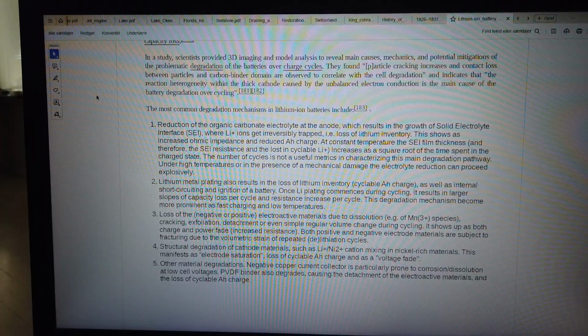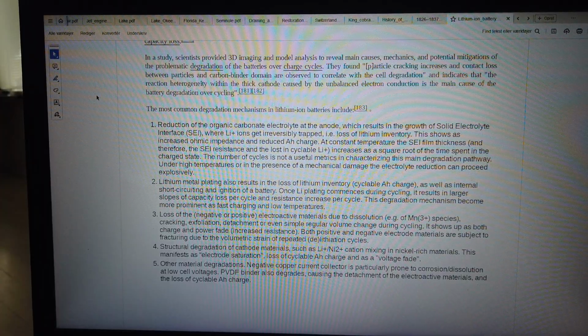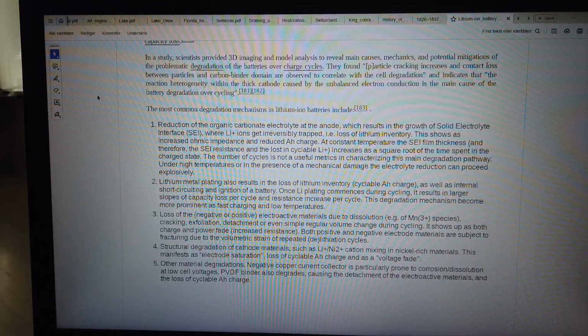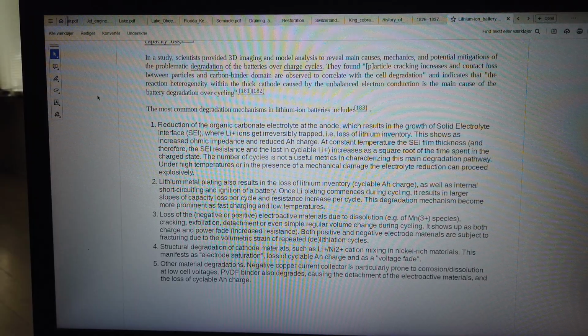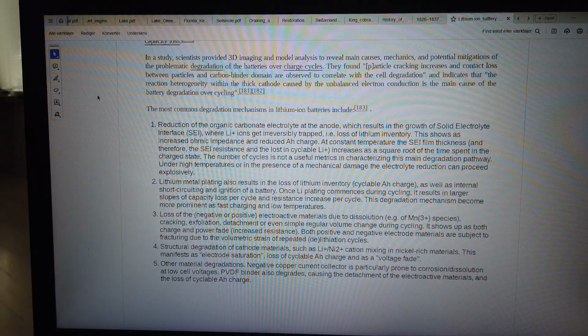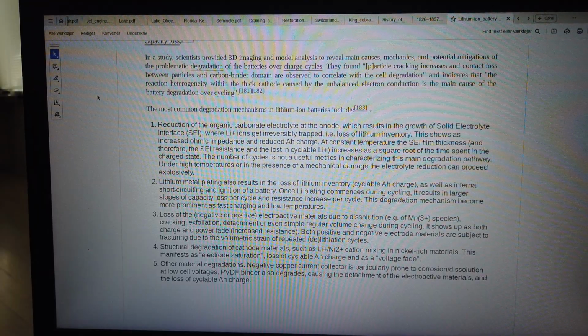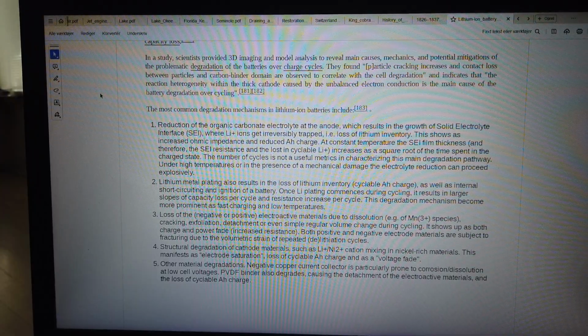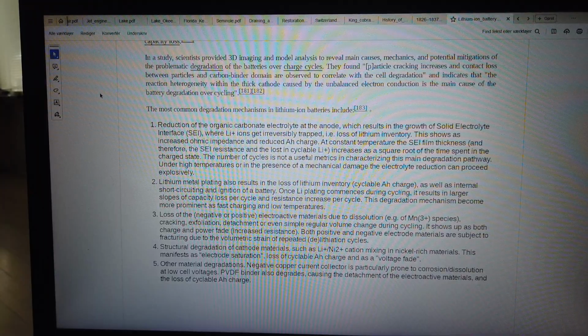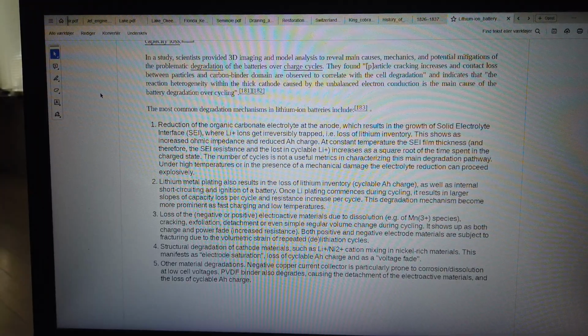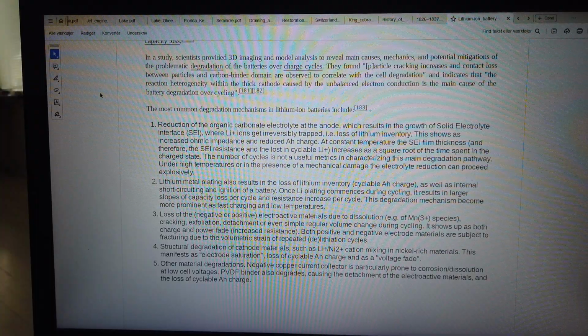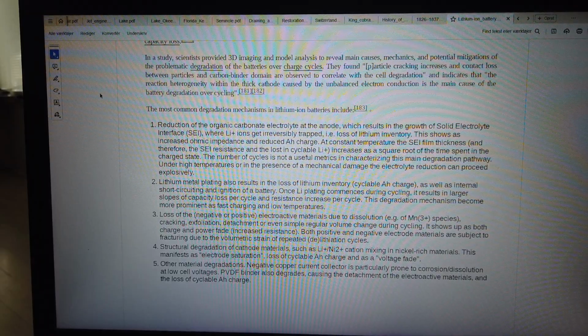Loss of the negative or positive electroactive materials due to dissolution, for example of Mn3+ species, cracking, exfoliation, detachment or even simple regular volume change during cycling. It shows up as both charge and power fade, increased resistance. Both positive and negative electrode materials are subject to fracturing due to the volumetric strain of repeated lithiation cycles. Structural degradation of cathode materials, such as Li+ and Ni2+ cation mixing in nickel-rich materials, manifests as electrode saturation, loss of cyclable charge and as a voltage fade.